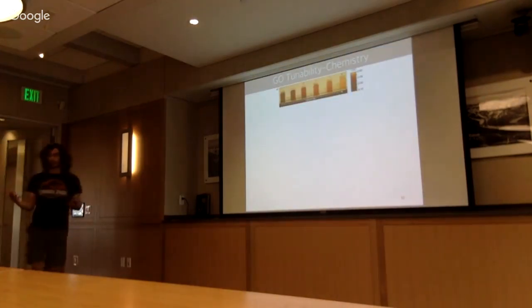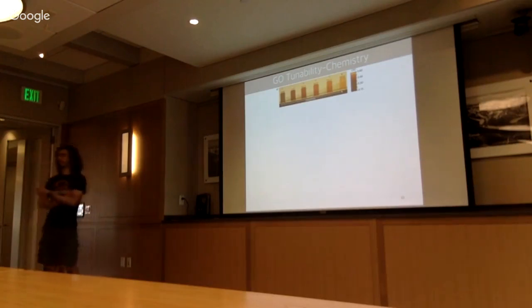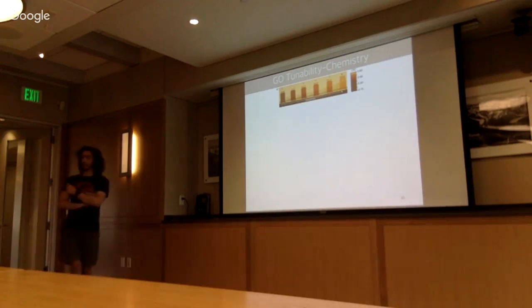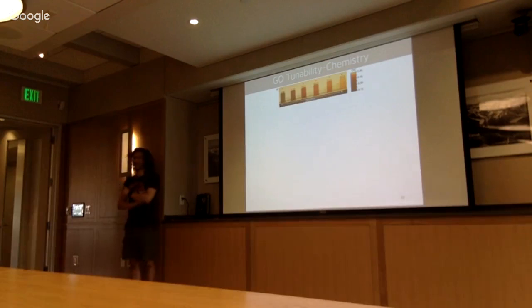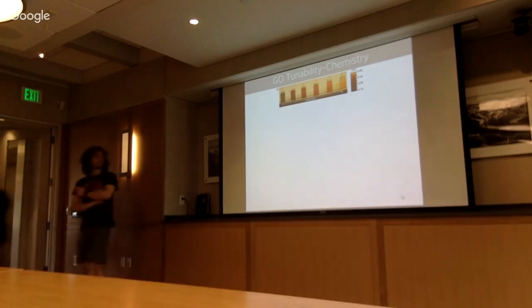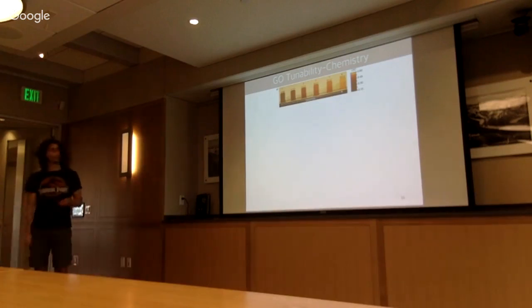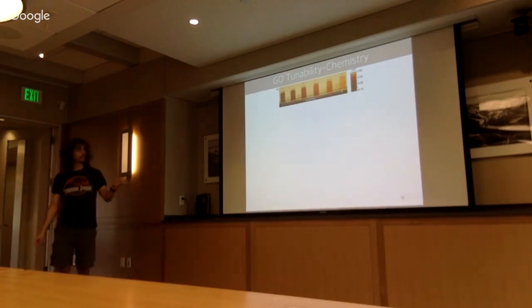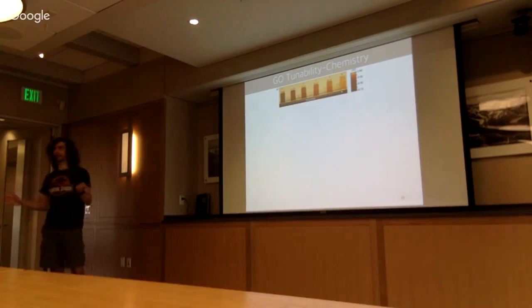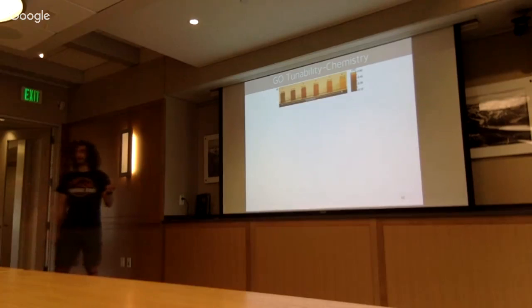But what is really cool about graphene oxide is that there are all these properties, but we can really tune these properties. And so what we can do, for instance, is tune the oxidation. So how much oxygen is contained in the graphene oxide? Here you have 6 samples, and what I'm varying here is the amount of oxygen. And you can see it goes from a dark to a more yellowish solution. And these graphene oxide flakes are suspended in the solution.